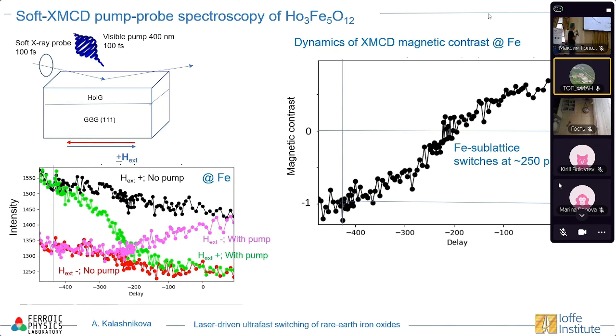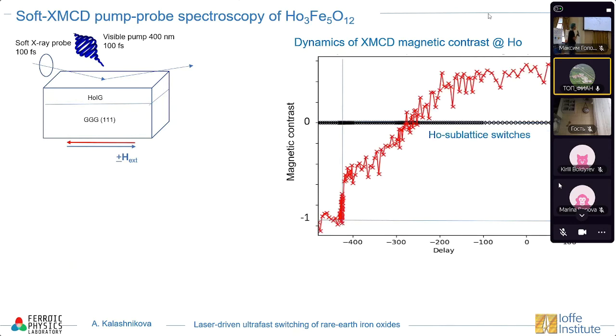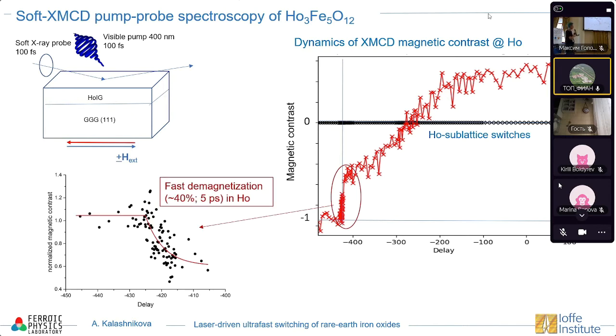And most importantly, that's quite a slow process. Nothing really happens at the short time scales. Now, if we look at holmium, we can do the same procedure. We also see this kind of slow dynamics, but most importantly, at short time scales we see a really fast drop of the signal. We can look at this closer. It's not very good statistics, but we can see that there is a characteristic time scale of the order of 5 picoseconds, and the drop is of the order of 40%.